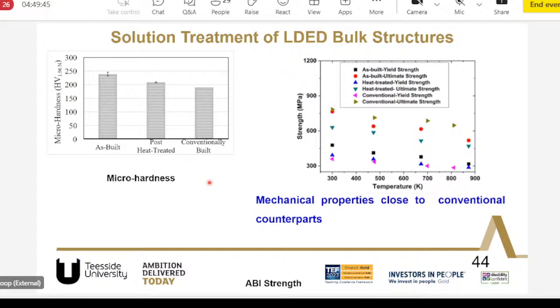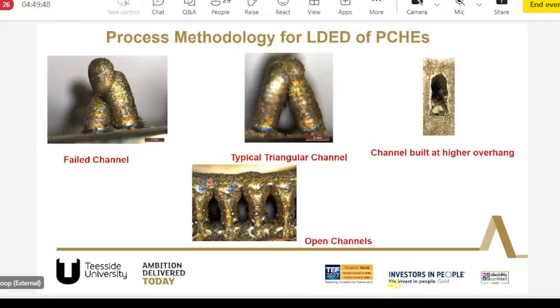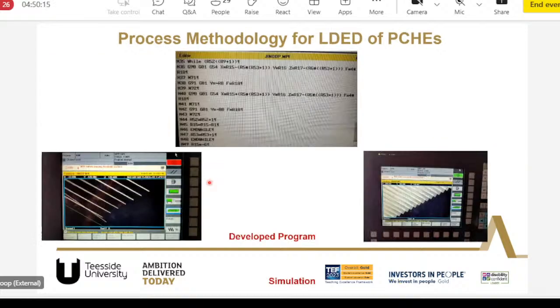And then we went into the development of this heat exchanger. It had a long struggle. We had failed channels in the beginning, then we started developing the process. When you start making these sorts of channels using additive manufacturing, the major part is the fine optimization, the fine thin line between the different process parameters. We need to optimize these process parameters carefully to obtain these channels with a high quality. So we could find this narrow gap where we could optimize the process,